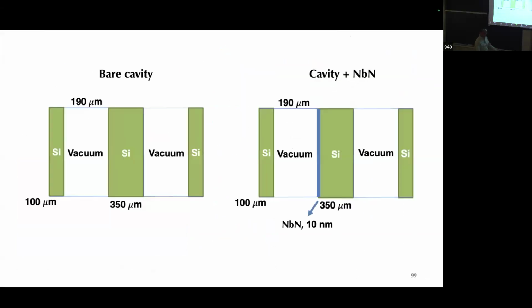Right. So in free space, it has been demonstrated that if you irradiate a superconductor with photons smaller than the BCS gap, you can modify the equilibrium distribution of quasi-particles that effectively increases the TC. That's called the Eliashberg, or classical Eliashberg effect. And there have been theoretical predictions about a quantum Eliashberg effect, where you use a cavity whose resonance photon frequency is below the BCS 2 delta, that's supposed to increase the TC. So the short answer to your question is